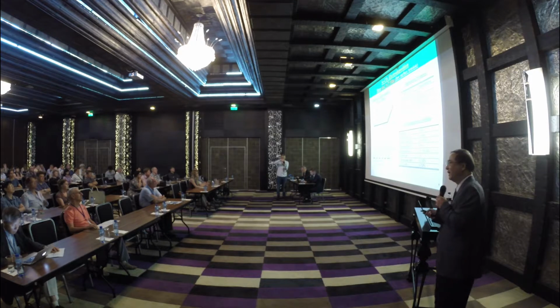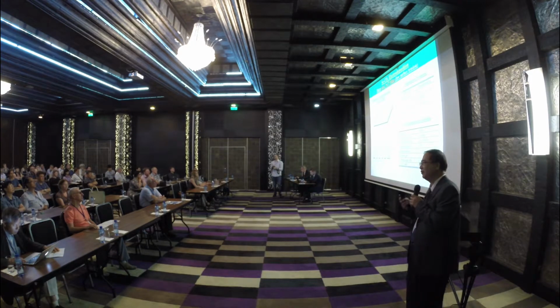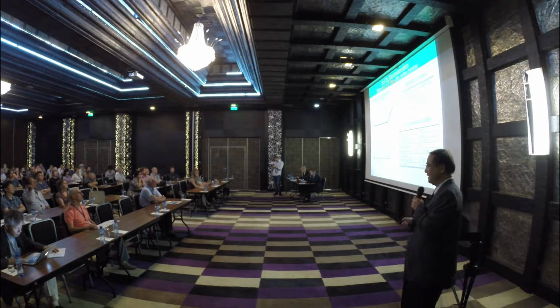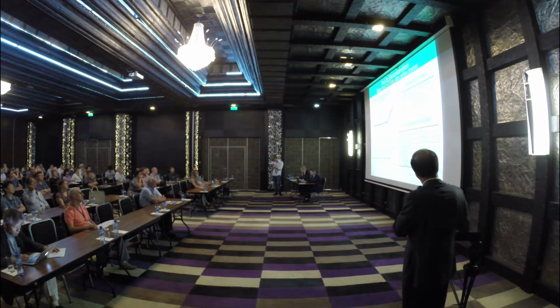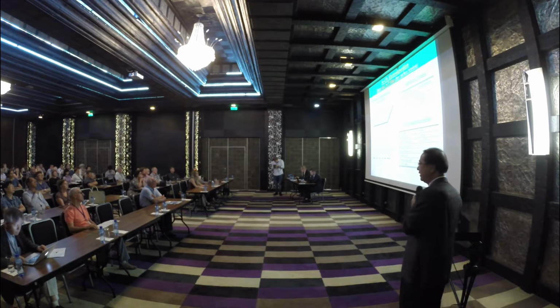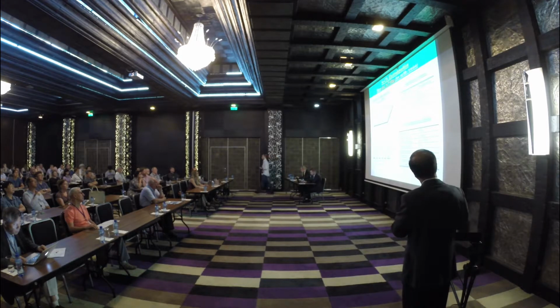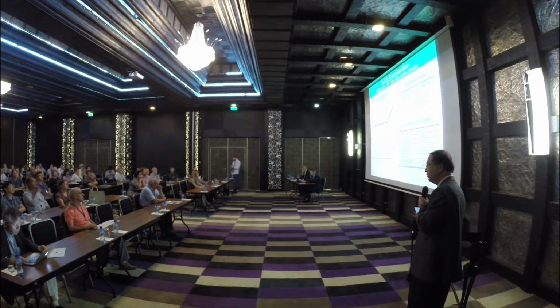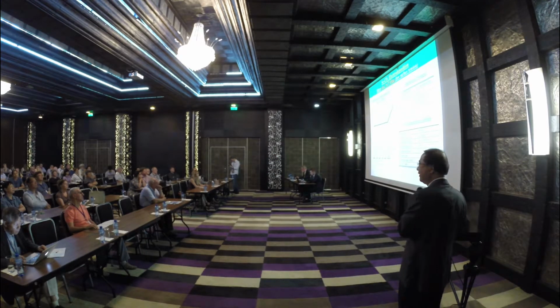So we would like to find a new application for supercritical carbon dioxide deposition, because as I mentioned earlier, supercritical carbon dioxide has a unique property that is low surface tension. We would like to use the low surface tension to see if it is possible to increase the filling of metal into micro holes with high aspect ratio.